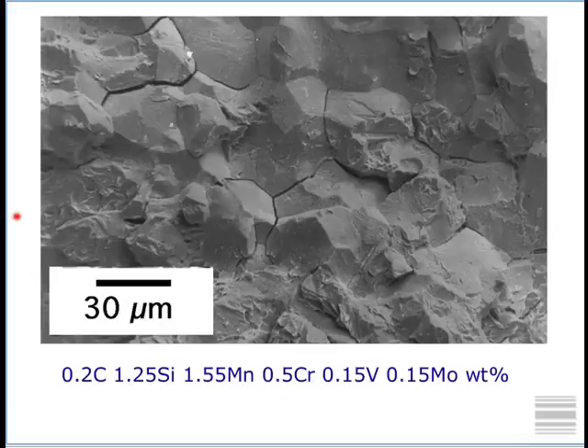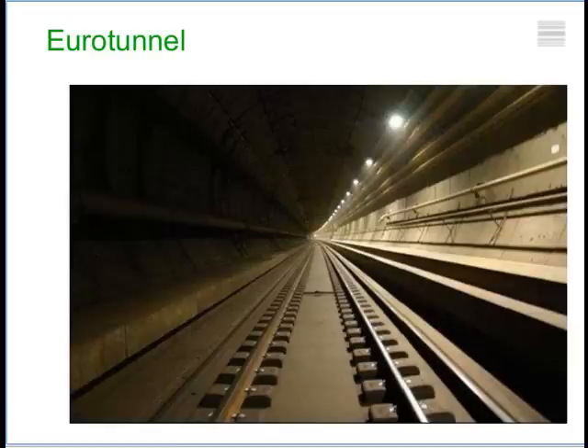Now, of course, I could say, let's remove the phosphorus from the steel. But a steel producer will tell me that if I want to make large quantities, that's an impractical idea because it's expensive to remove phosphorus. We have known for almost 60 years that if we add about a quarter weight percent of molybdenum, that stops this embrittlement. The mechanism by which it stops is complicated, but it works. So simply by adding a quarter weight percent of molybdenum, the problem was solved.